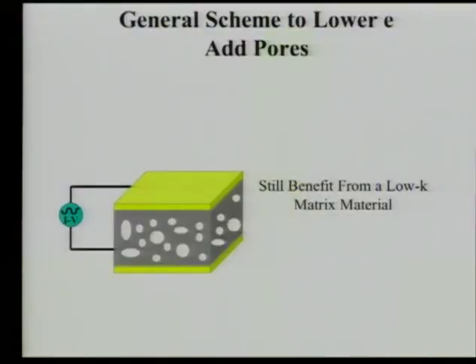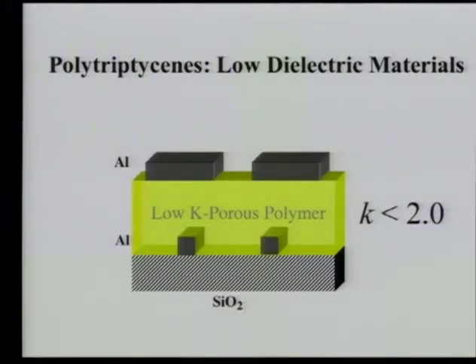And it would be great if we could do it with vacuum, but vacuum is not a very good structural material. We need something that's a little bit better. Most of the ways that people have done this with soft materials is they've made Swiss cheese. You take other materials that are stable, and you pattern them and you put pores in them. The problem is when you make the Swiss cheese holey enough, often the mechanical properties go down. So that doesn't seem to be a winning solution. What we can do with a molecular architecture like this is we can make a very rigid material, something that has a high modulus, it's very hard, something that, ideally to get it inserted into fabrication processes, has to behave like silicon dioxide. Everything was optimized around silicon dioxide. You don't want to give them something that looks like silly putty, and you're not going to get there. In fact, when I talk with semiconductor manufacturers, they're more interested in mechanical properties than the dielectric constant.